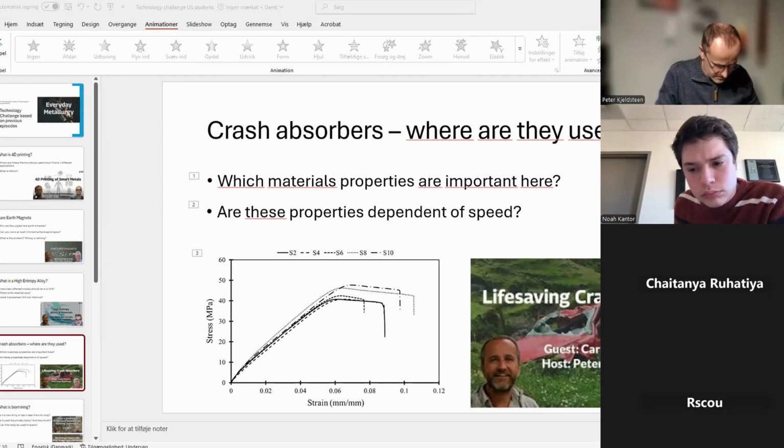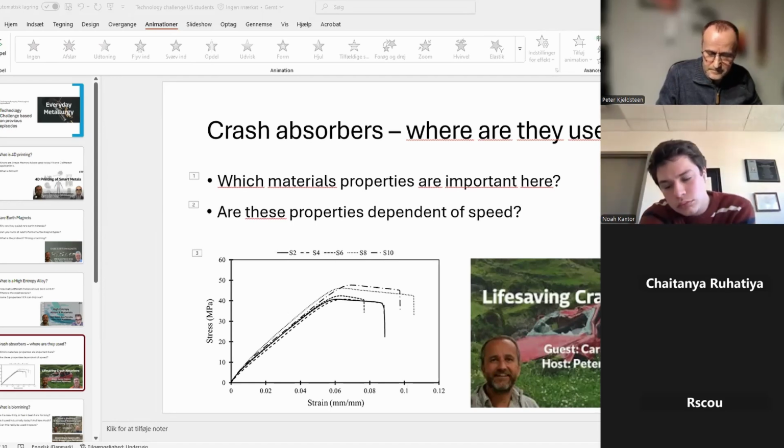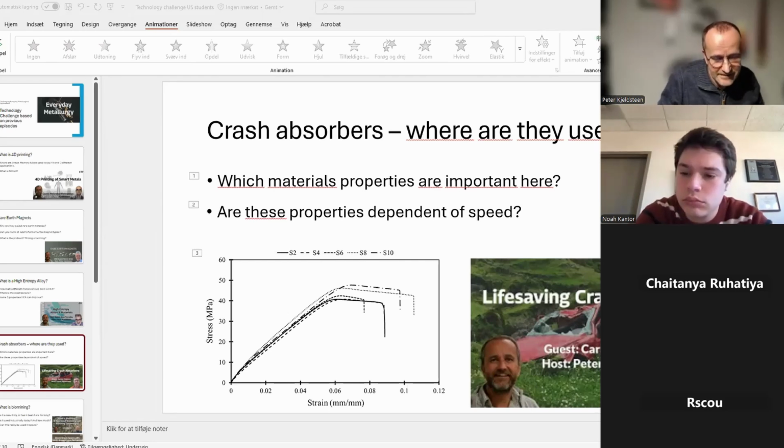So the tests we did here at WPI are lap shear, the peel test, and the impact energy test to basically break open this coupon joint using some adhesives and sealants, because today the welded joints have reduced a lot. The major joints in automobiles are adhesive and sealant based, because these joints decrease the weight of the car and increase the fuel economy, and at the same time give the same kind of crash resistance and joining properties. So we tried different rates, but all those rates are standard, what GM or Ford will put out in their standardization sheet.